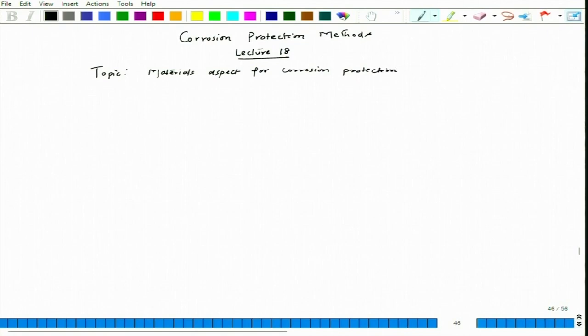Till now we have seen the effect of composition, and we started working on the effect of microstructure. At least in case of stainless steel, we have seen that if we increase the chromium content beyond 12%, corrosion resistance of the steel improves. If we add molybdenum, pitting corrosion resistance improves. Again, if we reduce carbon content, corrosion resistance improves.